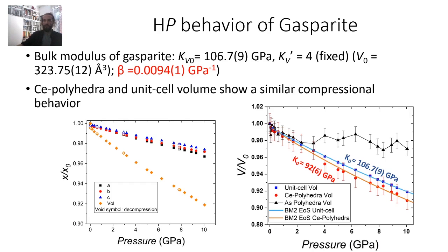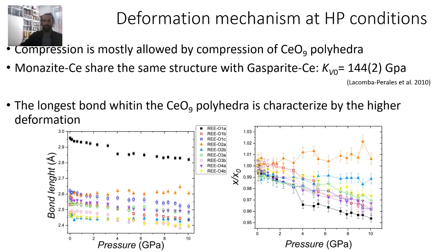The diagram also shows the evolution with pressure of the arsenic tetrahedron. Except for a slight compression in the lower pressure range, it doesn't contribute to accommodating the gasparite bulk compression at pressure greater than 3 gigapascal. However, the population of the tetrahedral sites apparently plays a significant control on the bulk compressibility of the monazite-like structure. In fact, the presence of the larger arsenic in place of the smaller phosphorus leads to a bulk modulus 40% smaller with respect to that reported in literature for cerium monazite.